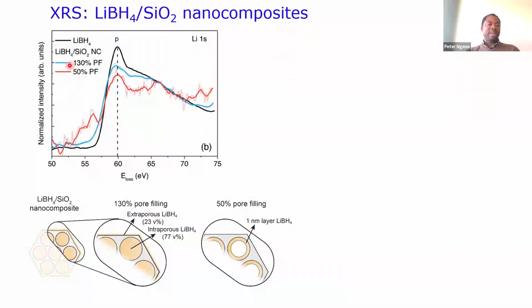Because in this case, you also have a huge contribution from the bulk. And this is what you see here. If you start with this 130% pore filling, where we fill everything, and we compare the bulk lithium and the nanocomposite, we do see there is a slight change, but we cannot conclude more. If you now have about 50% pore filling, already you see there's an extra contribution here from the lithium, and the contribution of the bulk-like has actually reduced, and we now have some other features that we will talk about. But basically, by playing with the concentration, we can even go to 30% or even 15% pore filling, where you begin to see only the interface composition.